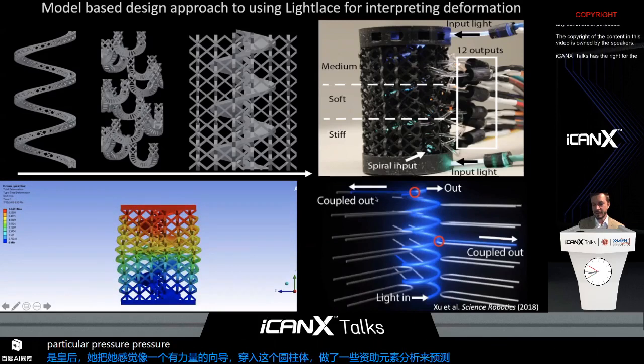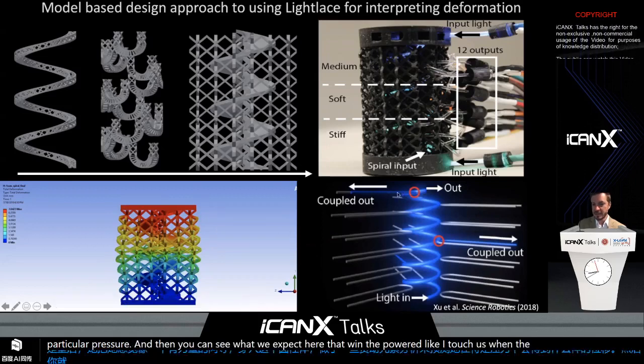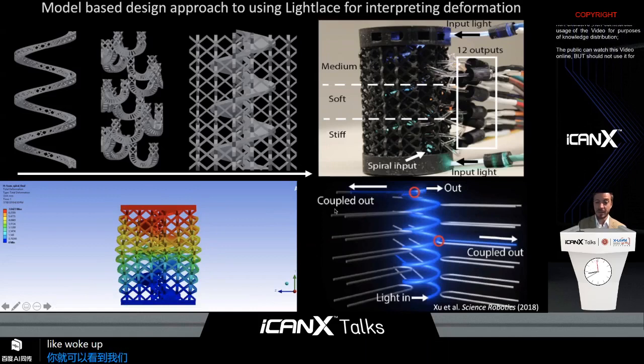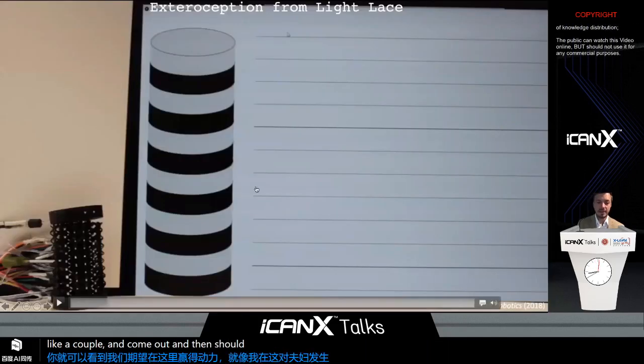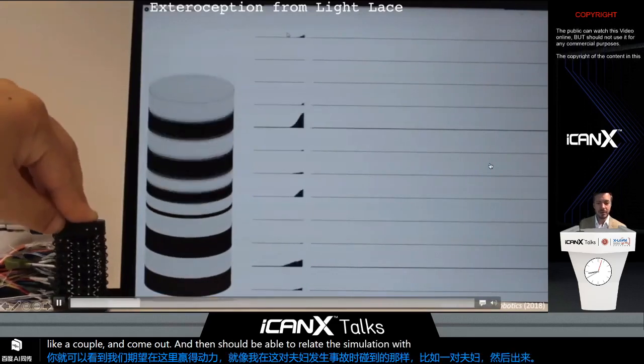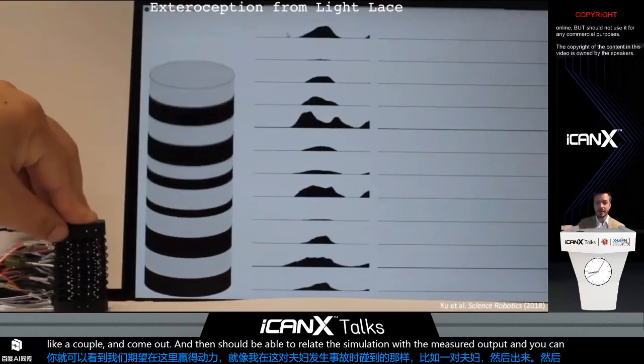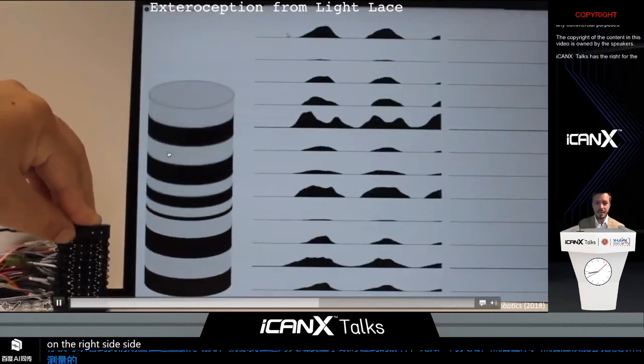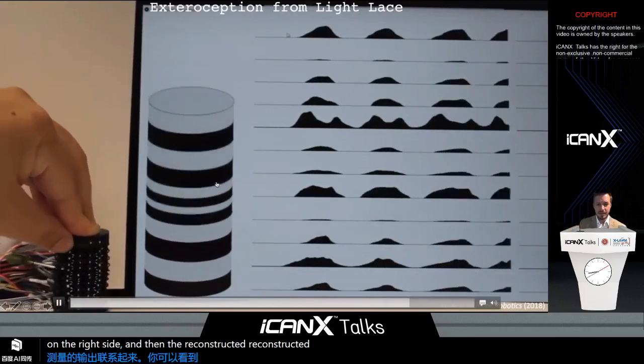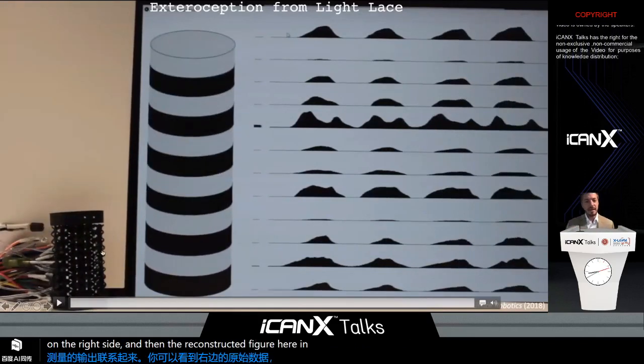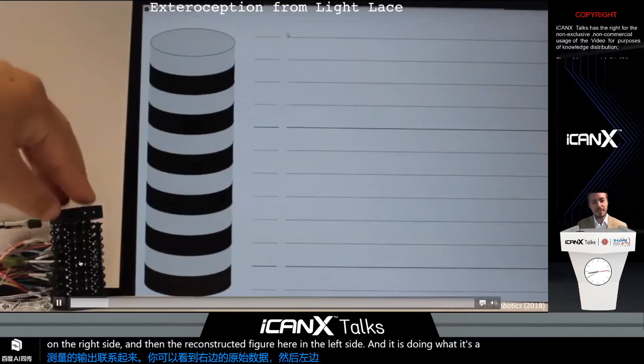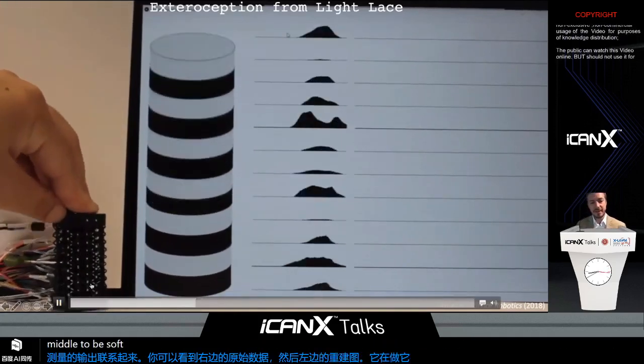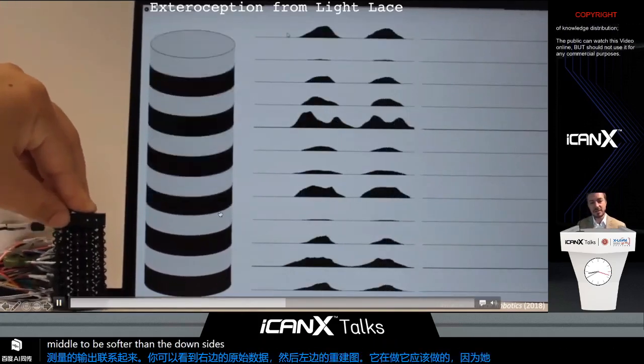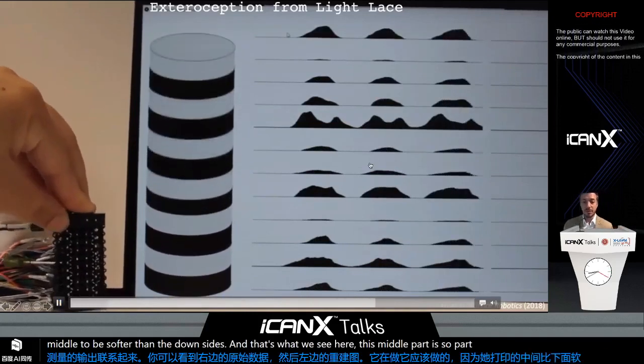And then you can see what we expect here, that when the powered light guide touches one of these incident ones, light will couple and come out. And then she should be able to relate the simulation with the measured output. And you can see the raw data on the right side, and then the reconstructed figure here on the left side. And it is doing what it's supposed to, because she printed the middle to be softer than the outsides. And that's what we see here. This middle part is displacing much more than the tops or bottoms.